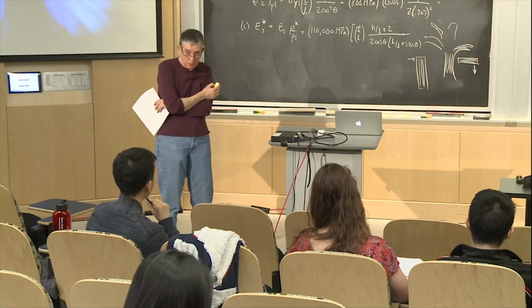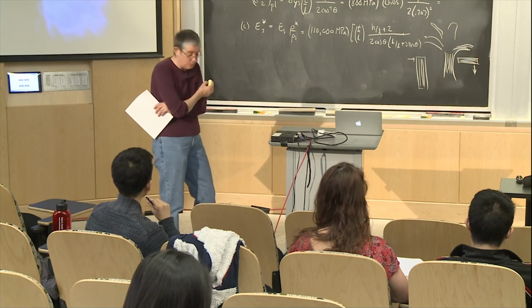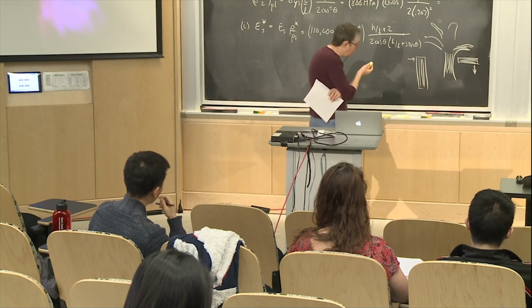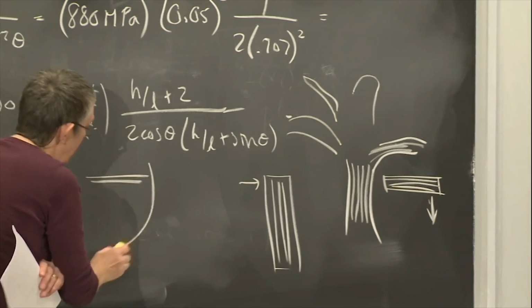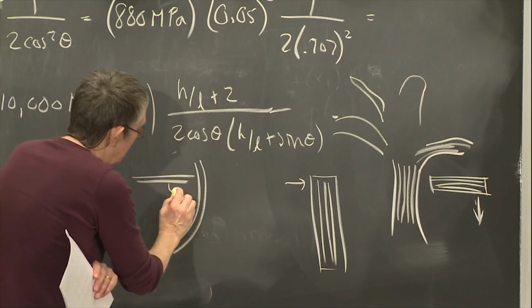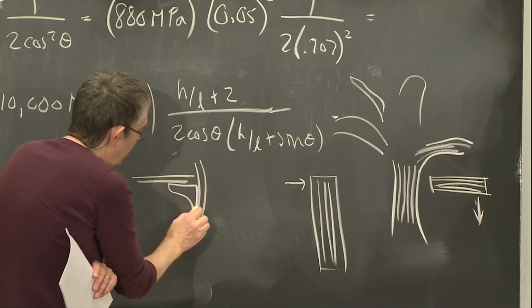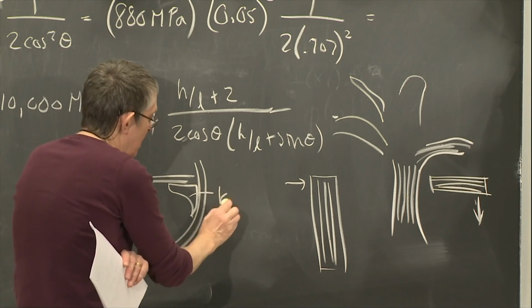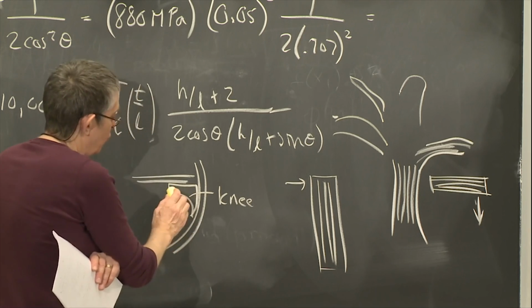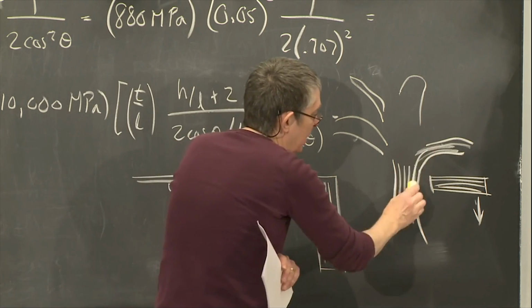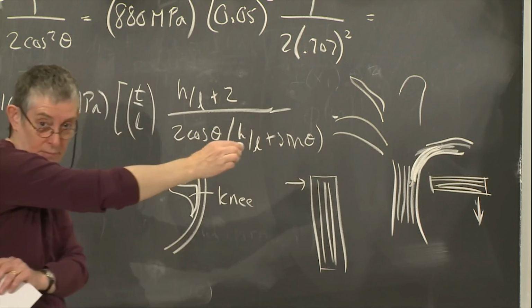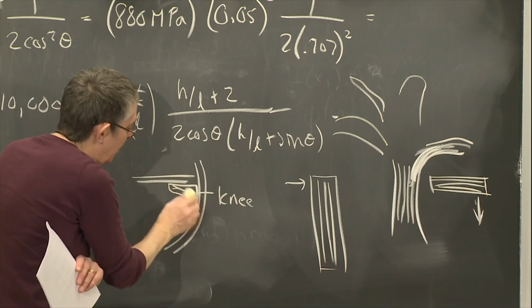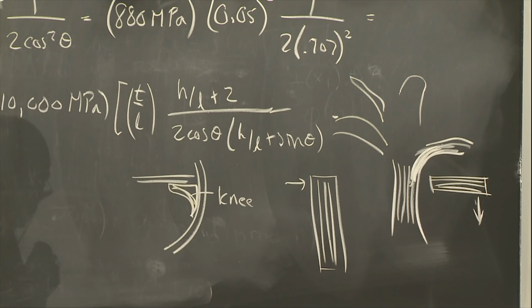And you remember when I talked about the old wooden sailing ships, when they made them, if this was the deck here and that was the hull there, they would get pieces of wood to fit in here that were called the knees. That was the knee. And they would try to get a piece that was from a branch like this. And they would try to match the curve of that joint with the branch with the curve that they needed in here, so that the grain followed the pattern of what they needed for the boat.